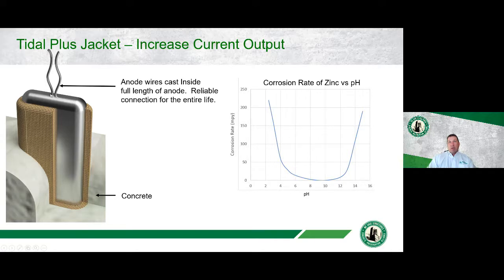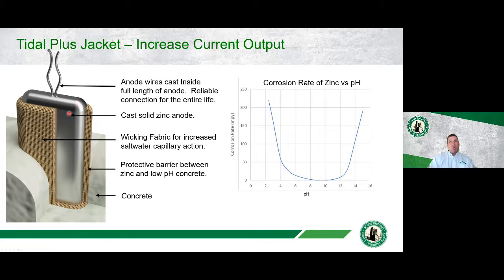The wicking anodes are made of zinc anode. There's a zinc anode inside. It's a solid cast core on the inside. There are tie wires that are cast through this solid core. So as the zinc is consumed, obviously it's going to be consumed and oxidizing from the outside in. As it's being consumed, our electrical connection or our metallic path from our anode to our steel is always remaining a good connection. The other thing that happens is we have that wicking fabric that completely surrounds our anode and allows the seawater to basically flow around or encompass this entire anode.